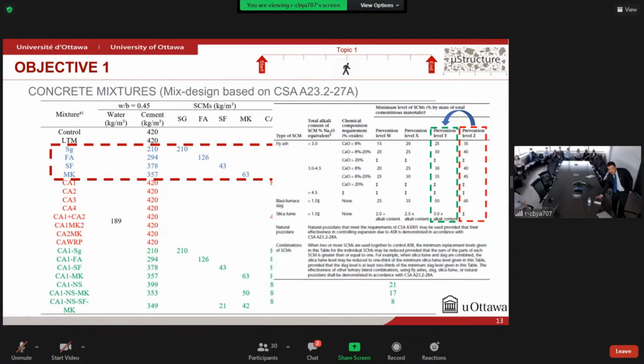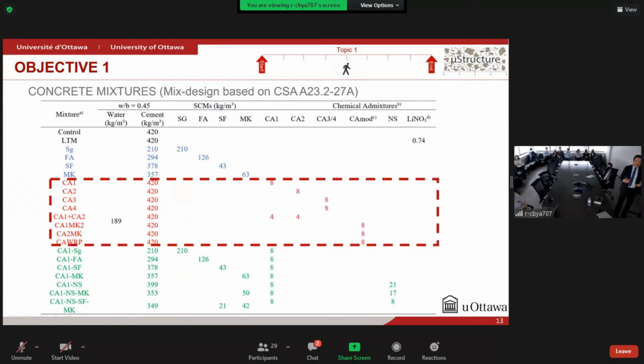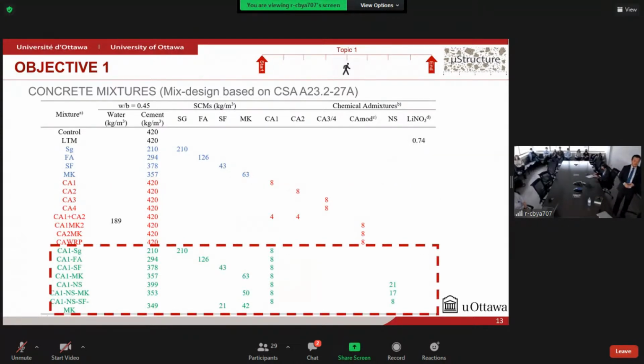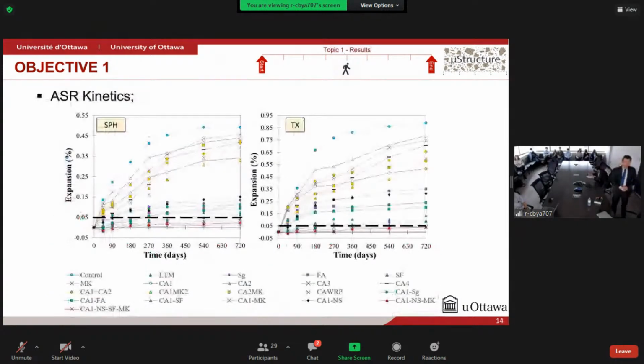Why? Because here we would like to then combine the different SCMs with crystalline admixtures to see how they would behave together. We use 4 different types of crystalline admixtures. Also, we mix them differently to try to enhance their healing behavior. And also at the end here, as I mentioned, we combine crystalline admixtures with SCMs. The results show that all mixtures we produced in the lab were able to first mitigate, change ASR kinetics, decelerating the reaction rate, but also decreasing the final expansion after 2 years of evaluation.